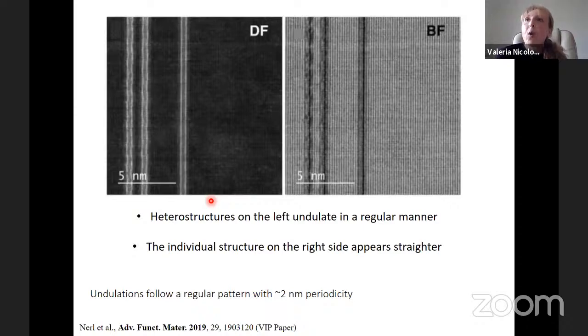Again, it was interesting to see how some of these heterostructures were not perfectly straight. You could see this undulated in a regular way. We understand that this is not a scanning issue because this is actually a very straight wire next to it. If there was a scanning issue, it would have been undulated all over the place. So it was an extremely complicated structure to resolve. These undulations always had a sort of 2 nanometer periodicity.